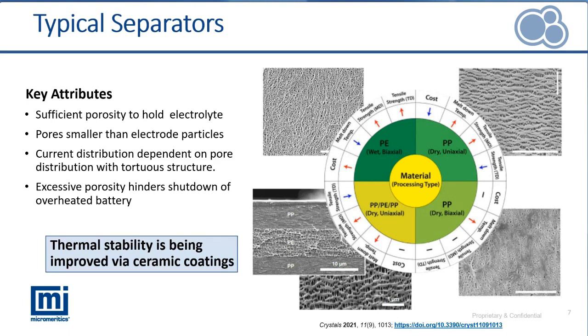Those are the leading technologies right now, but companies are also starting to look at different types of technology like biaxially stretching polypropylene, and they're now moving to technology where you have a tri-layer with polyethylene in the middle, which will shut down at a low temperature, and then polypropylene on the outside of the separator, which holds the mechanical performance so you don't get the electrodes touching and causing a fire. To further enhance safety and thermal stability, ceramic coatings are also being put on all of these different separators.